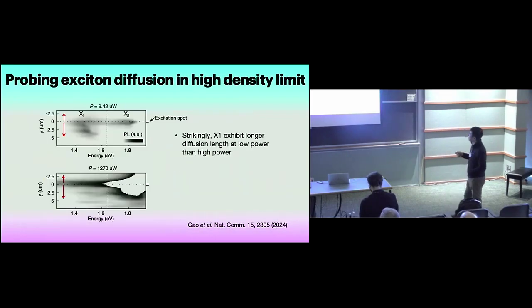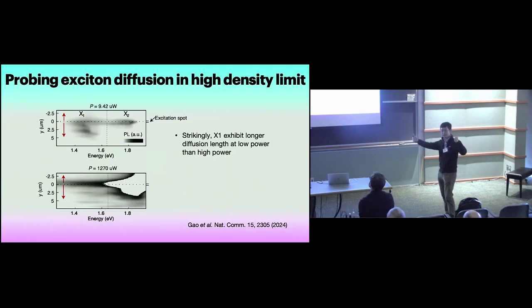Then we developed another technique to directly probe the exciton transport, which is to look at the exciton diffusion. So here I'm looking at the exciton diffusion in both real space along this axis and also energy resolved, so that I can only look at the X1 without looking at the more complicated X2. So this is just looking at this exciton diffusion in the simpler regime. If I compare this low power and high power regime, you see something quite striking, right? In the low power regime, you see that X1 is more spread out, but in the high power regime, the X1 is actually more confined. So this is in stark difference from what I showed earlier for the moiré-free system. There, when you pump the system, the excitons diffuse further away because of the repulsion. Here, initially it's spread out, but as you increase the pumping power, they actually become localized. So the diffusion length actually gets reduced.